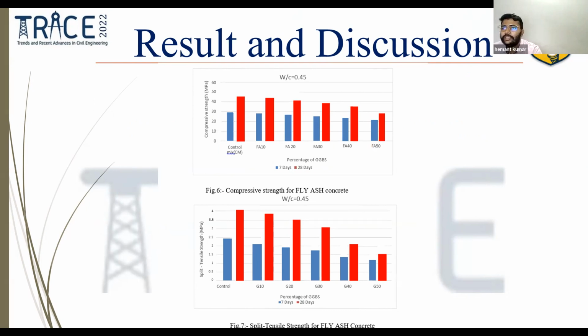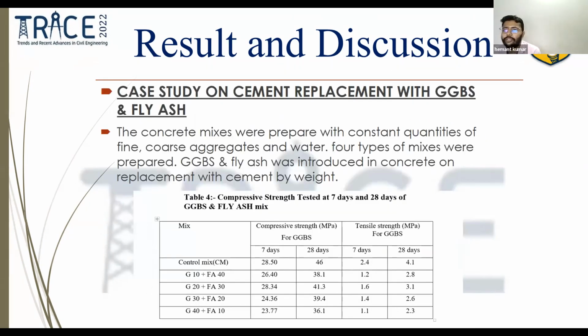Case study on cement replacement with GGBS and fly ash. The concrete mixtures were prepared with constant quantity of fine and coarse aggregate and water. 4 types of mixture were prepared. GGBS and fly ash are introduced in concrete as replacement for cement by weight. So here we prepare another 4 mixtures by varying the percentage of GGBS and fly ash while keeping a constant percentage of cement: G10 plus FA40, G20 plus FA30, G30 plus FA20, and G40 plus FA10.